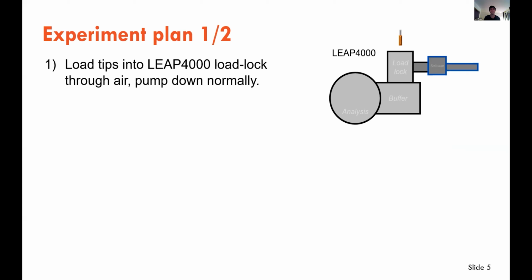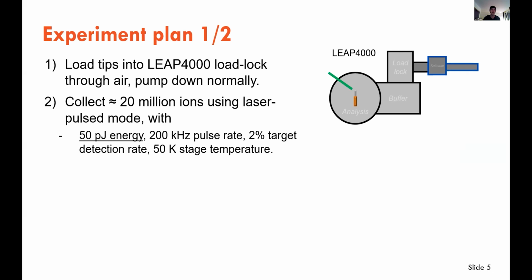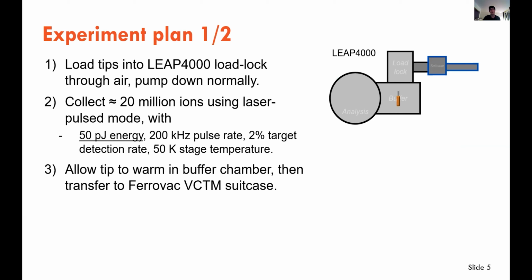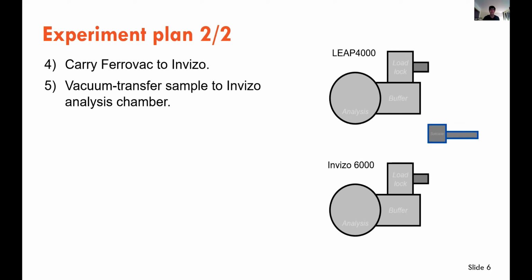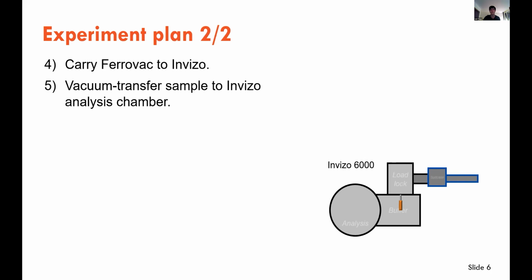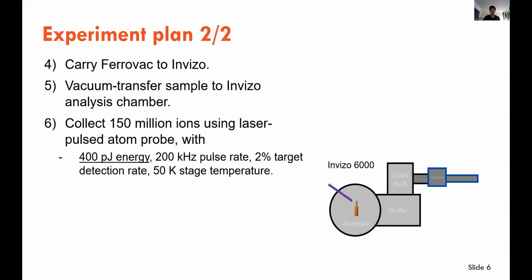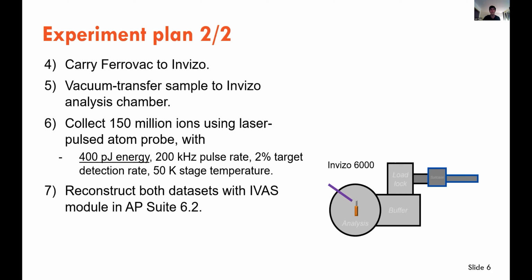So the experiment plan. At the University of Sydney, prior to the Invizo, our latest generation atom probe was the LEAP 4000. Specimens of the aluminium alloy were loaded into the LEAP 4000 normally. We collected 20 million ions using laser pulsed atom probe with 50 picojoules of energy. We then warmed it in the buffer chamber and transferred it into our Ferrovac vacuum and cryo transfer suitcase, though in this experiment we only used the vacuum part of that. We carried the Ferrovac over to our Invizo and then vacuum transferred the specimen into the analysis chamber. We collected 150 million ions using laser pulsed atom probe with 400 picojoules of energy, and then reconstructed both data sets using IVAS.